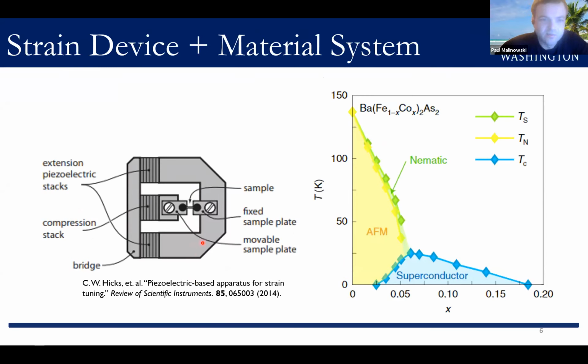So in order to apply strain to bulk single crystals, we use either commercial or home-built versions of the uniaxial stress device shown schematically here, originally developed by Cliff Hicks. Briefly, the way that this type of device works is that a bar-shaped sample is glued across a gap in a titanium scaffolding, which is attached to 3 piezoelectric stacks. And then by applying voltage to these piezo stacks, we can modulate the size of the gap and thereby apply strain to the sample. Furthermore, by cutting the shape of the sample appropriately, we can control the symmetry type of the strain that we're applying. So the data I'll be showing you has the crystal cut along the 110 direction, which will induce a mostly B2g type symmetry strain, which is the appropriate type for coupling in the ways I described on the previous slide.